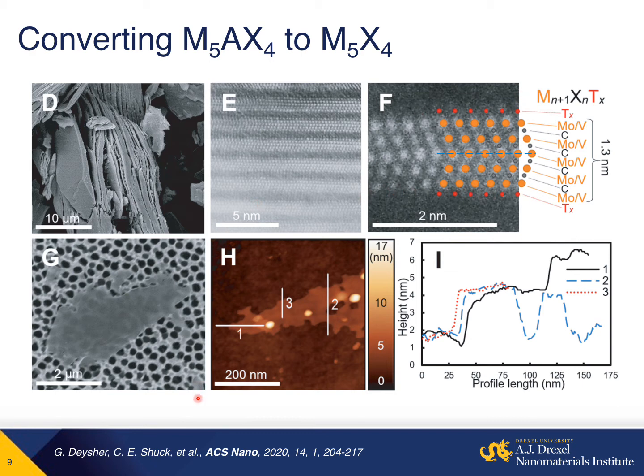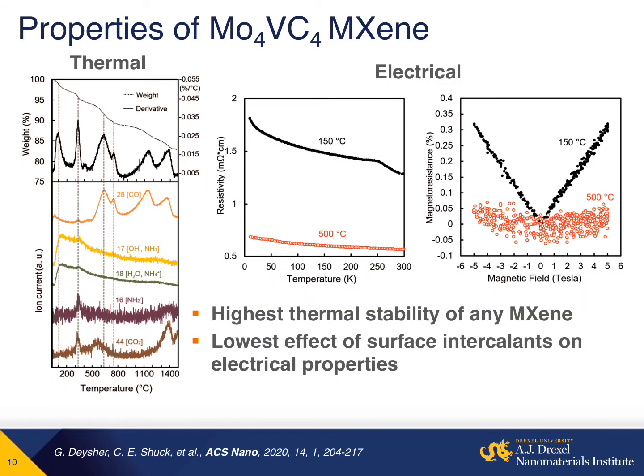We delaminated the MXene using tetramethyl ammonium hydroxide, and this is an image of a single flake deposited on an alumina substrate. And we used AFM to examine the thickness of it. So this is thicker than we would expect from just the structure, and this is due to the adsorbed gases still on the surface. After producing the MXene, we wanted to see if its higher thickness and unique structure led to any enhanced properties, initially beginning with thermal stability.